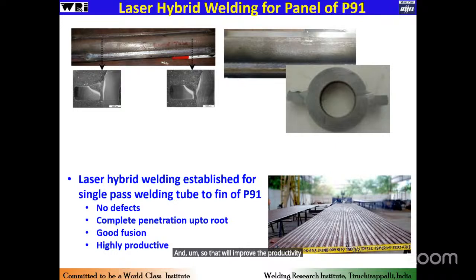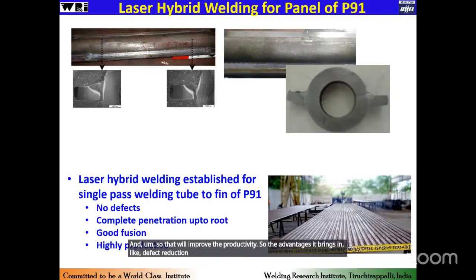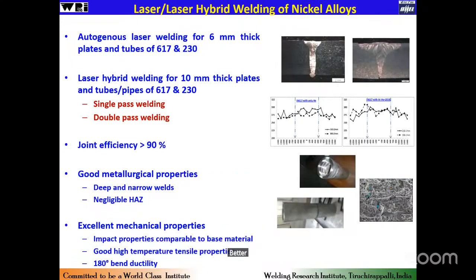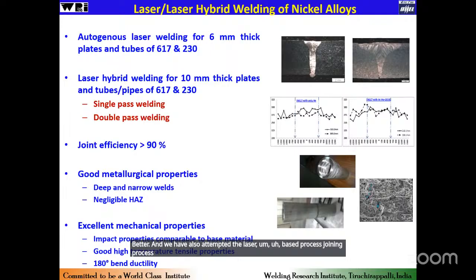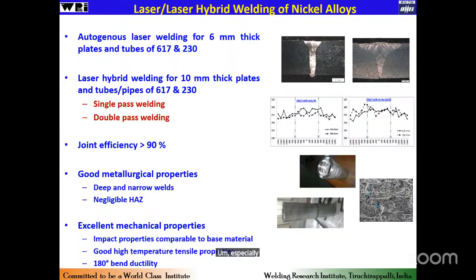So the advantages it brings in are defect reduction, single side welding from the top to achieve the entire penetration, and good fusion characteristics, and the productivity will be better. And we have also attempted the laser based process, a joining process for welding of tubular components, especially which is in the laser regime.